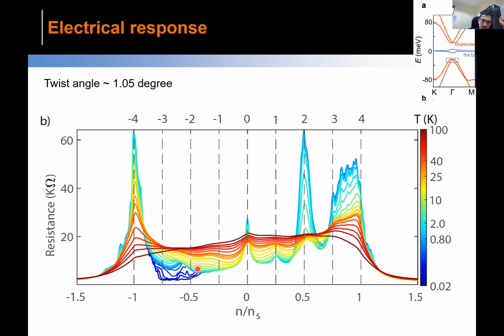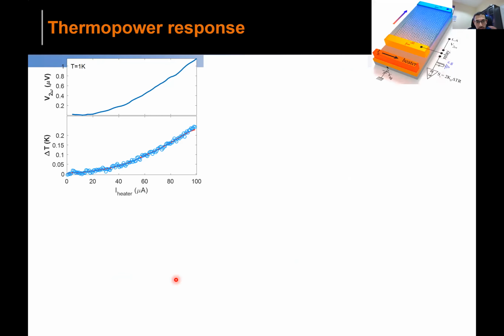Nevertheless, on the left side, you see the resistance saturation here, because this is a 2-probe measurement. We don't see resistance go to zero, but you see some signature of superconductivity. I don't have the time to show other details, but we see a signature of superconductivity in this device. Now, for the thermopower measurement, we pass a current through the heater. As I pass current through the heater, I measure this voltage and the temperature difference. These are the two things we have simultaneously plotted here as a function of heater current.